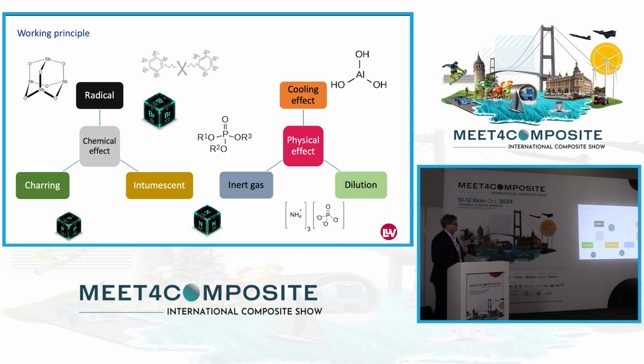And you have the physical effects. Very well known is a cooling effect by aluminium trihydrate. If you have a fire, you have a formation of water by the aluminium trihydrate, and this water is cooling the flame. It's very simple. In most cases, this is the main material used in the composite industry because it's cheap and it works. On the other hand, you have to use lots of material, 200, 300 parts in your composite, which makes your part very heavy and lowers the mechanical properties.